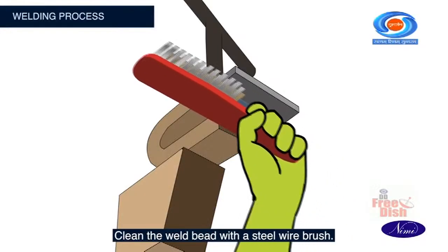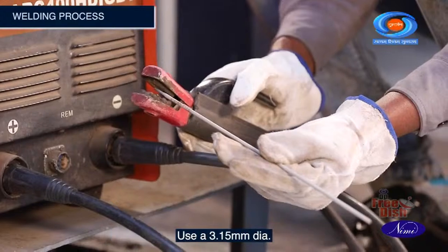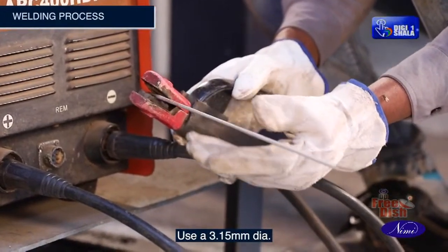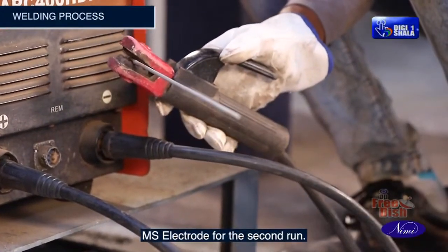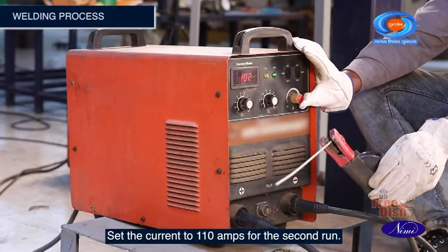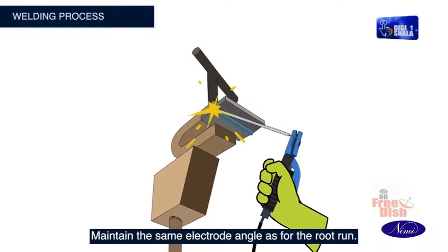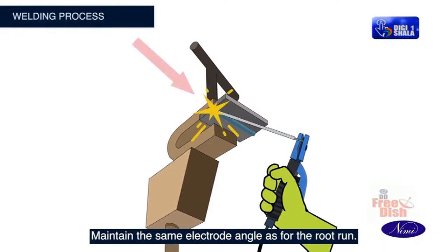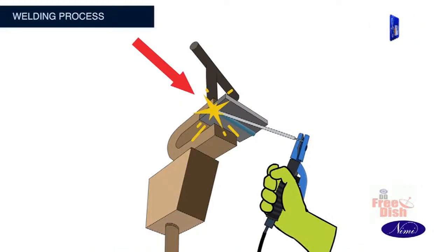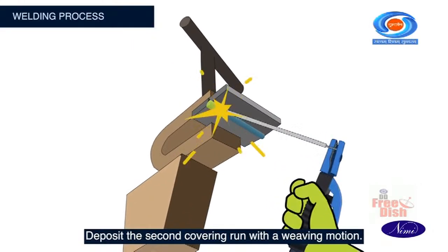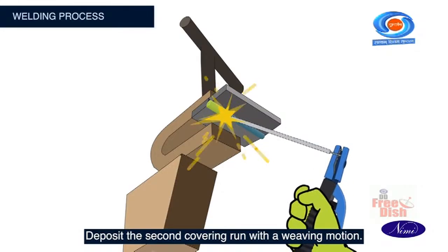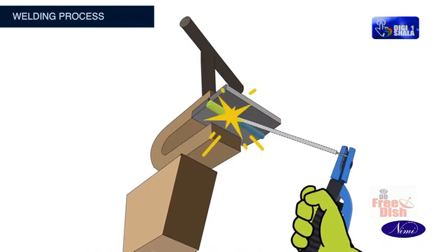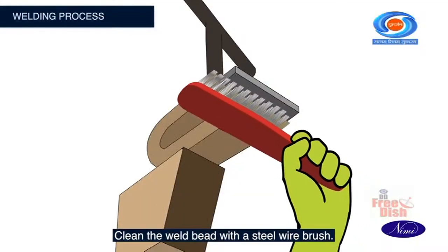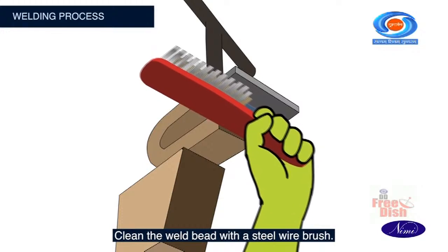Clean the weld bead with a steel wire brush. Use a 3.15 mm dia MS electrode for the second run. Set the current to 110 amps for the second run. Maintain the same electrode angle as for the root run. Deposit the second covering run with a weaving motion. Clean the weld bead with a steel wire brush.